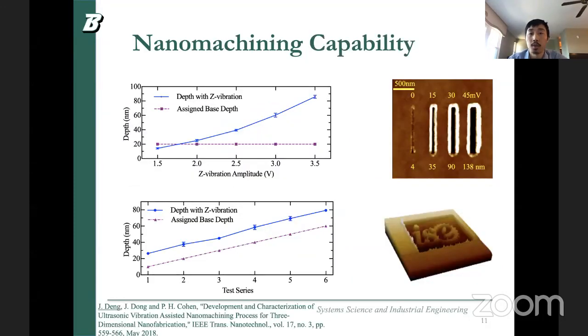So let me show the nanomachining capabilities with the vibration. First, we'll talk about the capability if we include the XY vibration in this nanomachining setup. This is the XY vibration effect. If we increase the amplitude of the vibration, we can directly increase the nanomachining trench width from 4 nanometers to 35, all the way to 100. Of course, we can go even larger because we can easily tune the input vibration amplitude. Therefore, we can control the width of the nanotrenches.